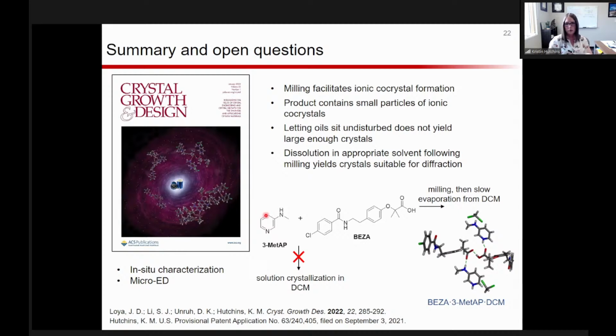And I think what was really interesting about this study and kind of shows the power of what the mechanochemistry is doing is that if you take the 3-methylaminopyridine and the bezafibrate and you dissolve those in dichloromethane, again, you get an oil and you don't get the product that you want. But if you go through the milling process and then you dissolve them in dichloromethane, we could get this solvate form. So clearly the milling is offering us a path that solution is just not, and pre-organizing these so that they will co-crystallize together.